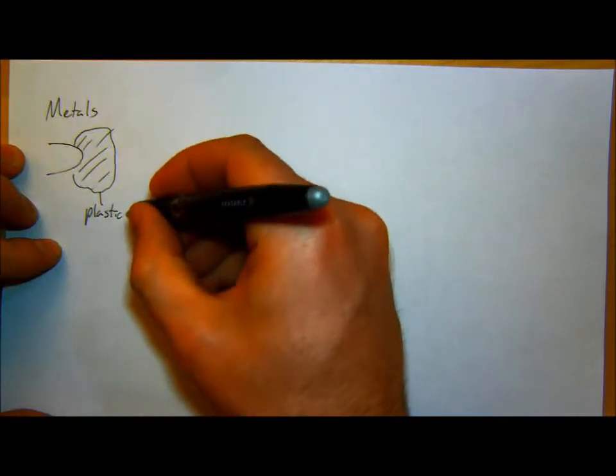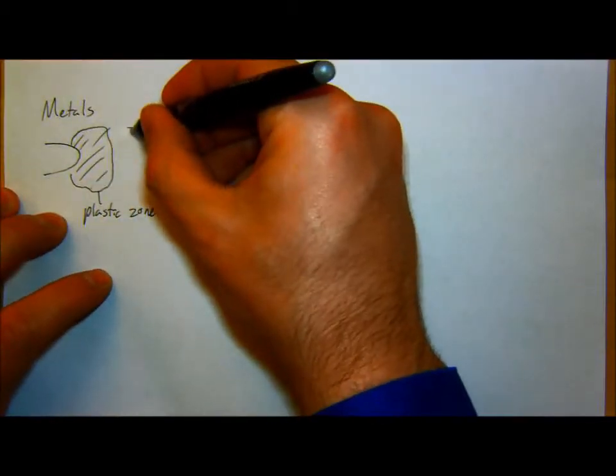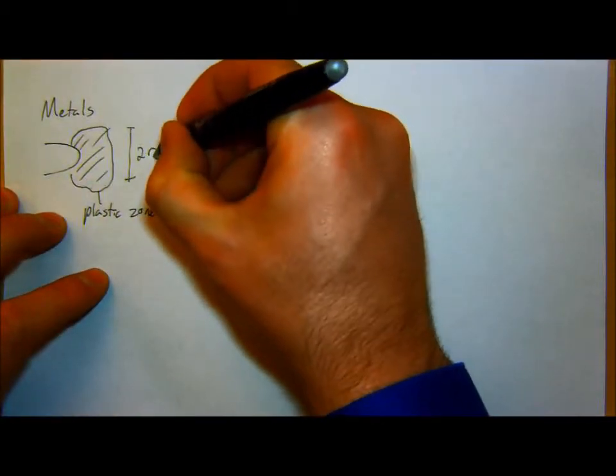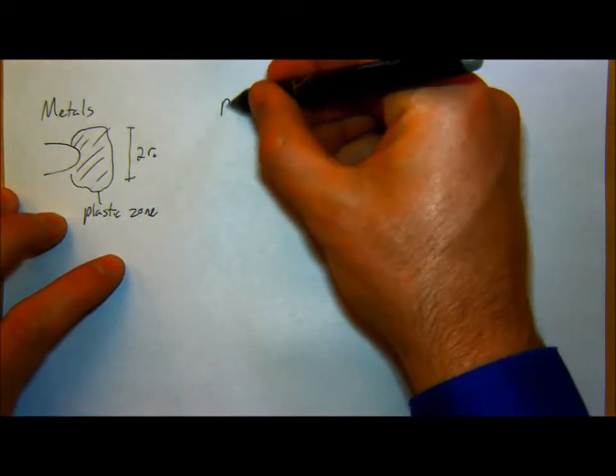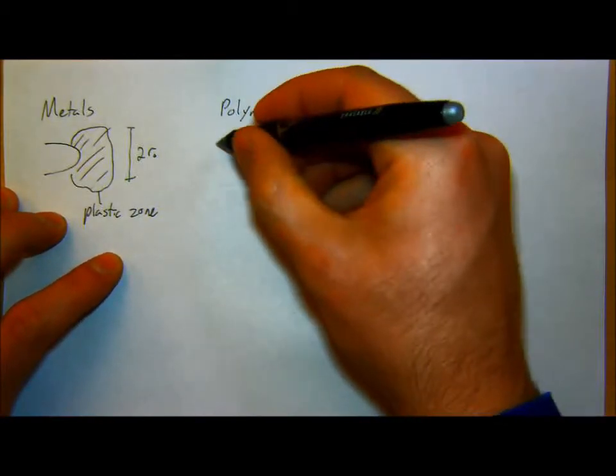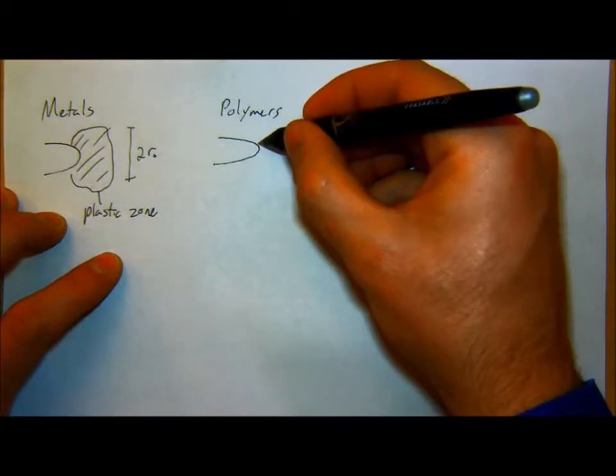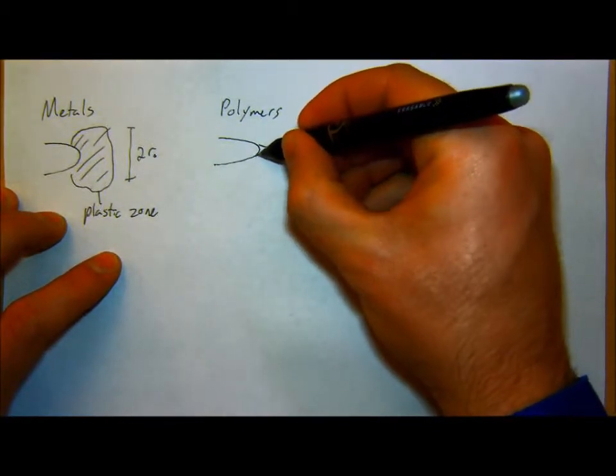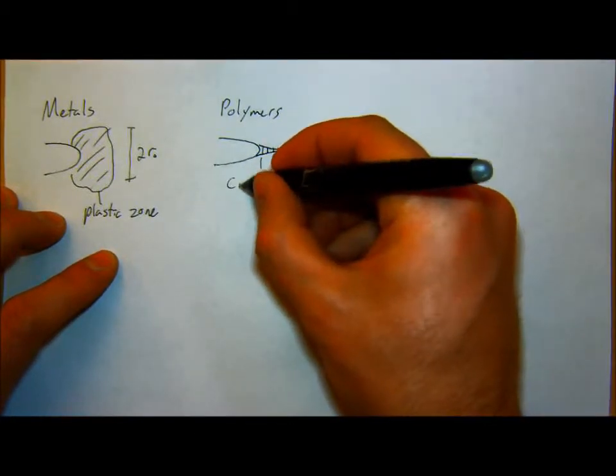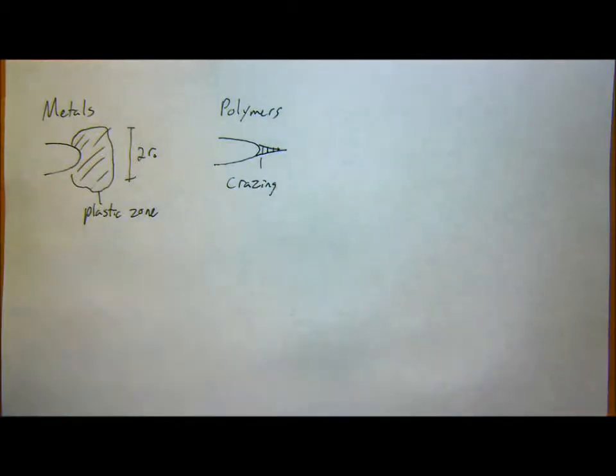For polymers, instead I have something where it'll actually start to split at the edge of that tip. So I get a phenomenon known as crazing, which basically, because a polymer itself is chains of molecules held together, as I start to pull it, those will start pulling apart and I'll get bridging of that polymer across the crack. And so you'll get long strings of polymer bridging the tip of a crack in a phenomenon known as crazing.